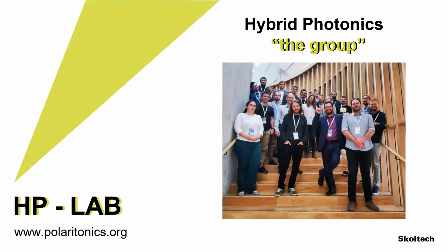But of course, one needs to consider how strong is the interaction between polaritons. Because if you remember from the work on the optical transistors or the earlier work on the condensates, we saw that within a picosecond, we can flip states. So within a few picoseconds, I have strong enough interactions to switch things around, be it the spinor of the condensate or the coupling between condensates, and then when I deal with the polarization, the spinor, I have 320 picoseconds to do some operations.